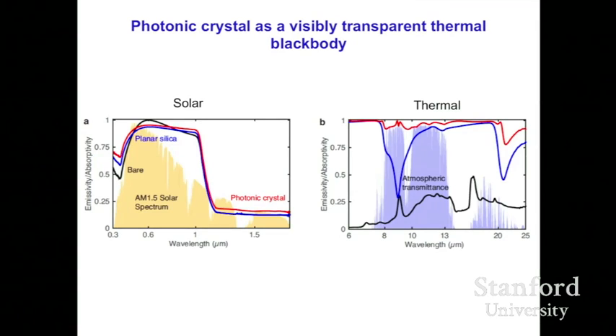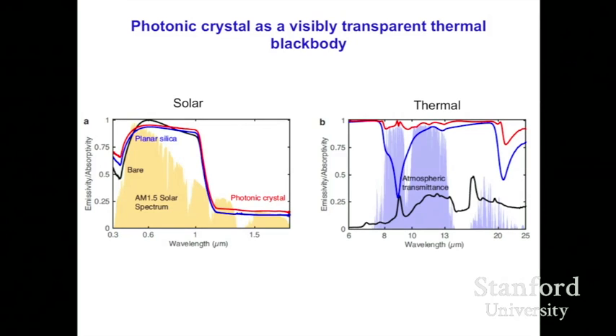Even though they have very similar visible or near infrared spectral characteristic, their properties in the far infrared is actually very different. The black curve here is the emissivity of the bare silicon layer, and you can see the emissivity is relatively low. The blue curve here is the emissivity of the structure consisting of a thick, uniform 500 micron thick layer. And as theory predicted, you indeed would observe a very strong dip in the 8 to 13 micron window, indicating that this is suboptimum as far as trying to emit thermal radiation in the 8 to 13 micron window is concerned. The red curve here is the emissivity of the silica photonic crystal. And you can see near unity emissivity over the entire thermal wavelength range.